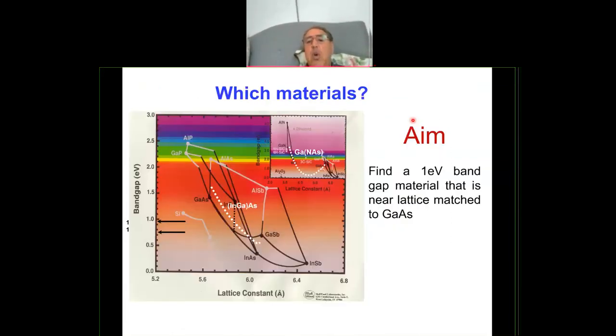I'm going to show you what kind of materials. So this is just showing you, for example, the band gap against lattice constant. Each time you want to grow a sandwich structure, you have to make sure that the semiconductors have the same lattice constant. Look here at the germanium, gallium arsenide, aluminum arsenide, they all have the same lattice constant. So you can grow them one on top of the other with no problem at all. So you can see here you go from 0.7 all the way to 2.2 EV. So you can choose this as you like.